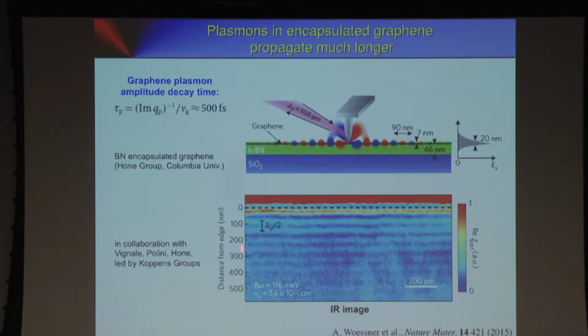So these graphene plasmons propagate over many hundreds of nanometers, that means over many wavelengths, but still they are damped out. I mean, these are not like free space photons. These waves have a certain damping because they are heavily coupled to the electron gas itself. Nevertheless, we get here a 500 femtosecond lifetime, and if one compares that to a plasmon in a metal in the visible frequency, then this is a factor of 10 better. So these waves don't propagate very long because they are extremely slow. The group velocity is about 1% of the phase velocity of light.